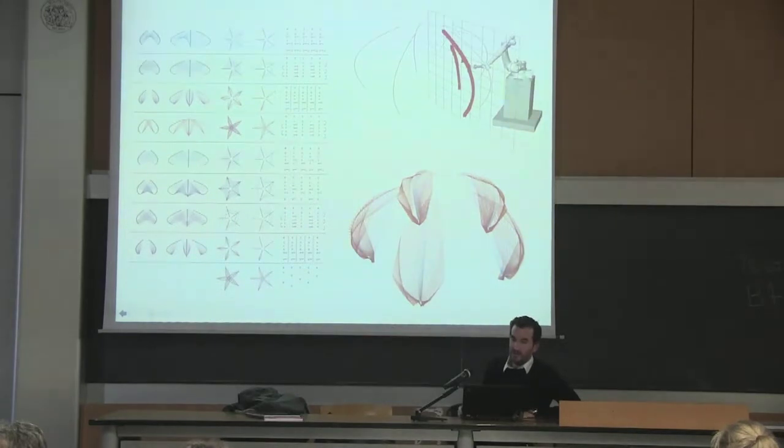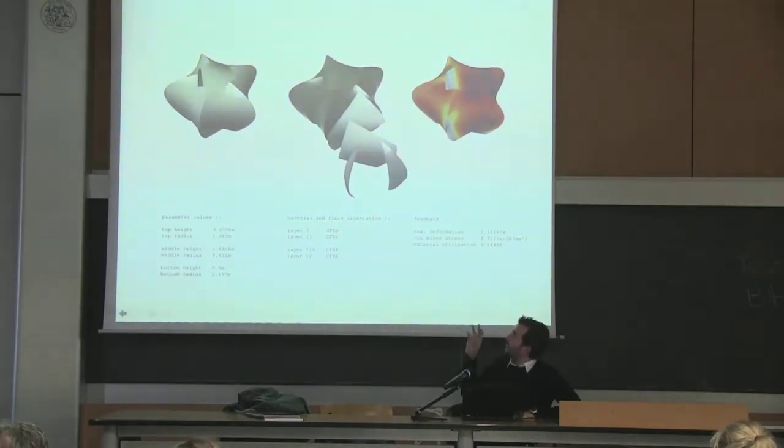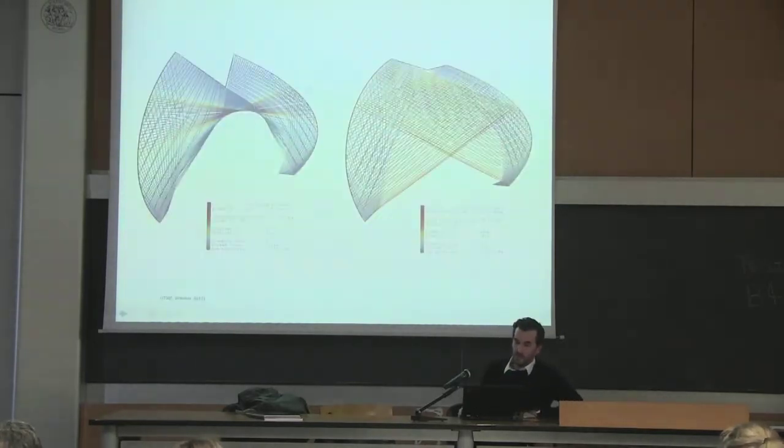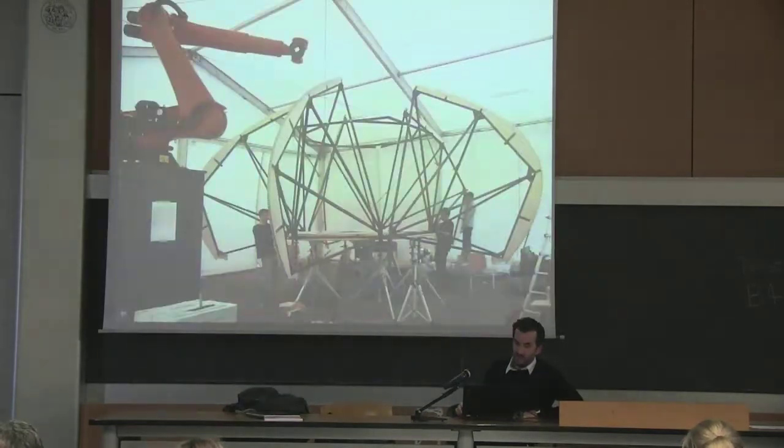These principles were then embedded in a comprehensive method for developing design techniques that unfold quite a rich repertoire of architectural morphologies, based on the quite complex relation between the geometry and the manufacturing process, where you have to understand that only at the very end of the fabrication process the part takes the final shape, because if you wrap fibers around a fibrous scaffold, it changes through the entire process. So our engineering partners simulated this process so that you can understand what the pre-stress is with which you need to lay the fibers to get a given result.